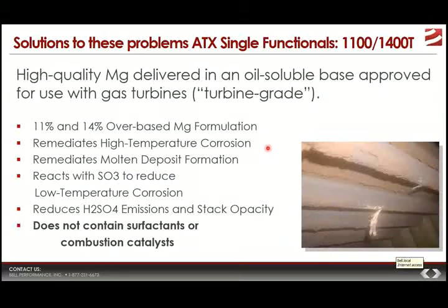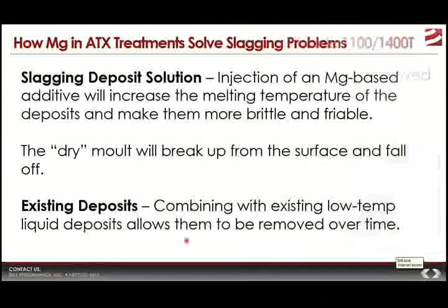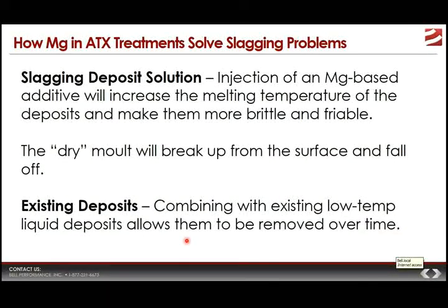Benefits you're going to get, like we said, you're going to fix high temperature corrosion. You're going to fix those semi-liquid or molten deposit formations. You're going to neutralize SO3, which helps with low temperature corrosion. You're going to reduce emissions of sulfuric acid, and you're going to reduce stack opacity. Again, the difference between single function and the multifunction: 1400T and 1100T do not contain the surfactant package, and they do not contain the organometallic combustion catalyst.